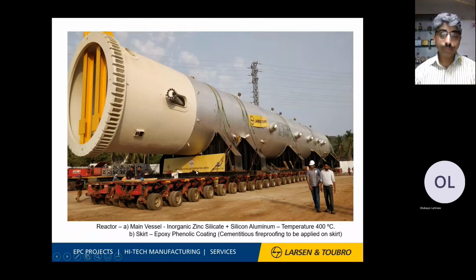Coming to the photographs or the articles, this is the fireproofing area. So you always find different coating systems. If you see the skirt, epoxy phenolic coating, that is cementitious fireproofing, that is always for fireproofing applications. And the rest of the paint, that is inorganic zinc silicate and silicon aluminum. What I say, it is for 400 degrees centigrade temperature resistance applications.